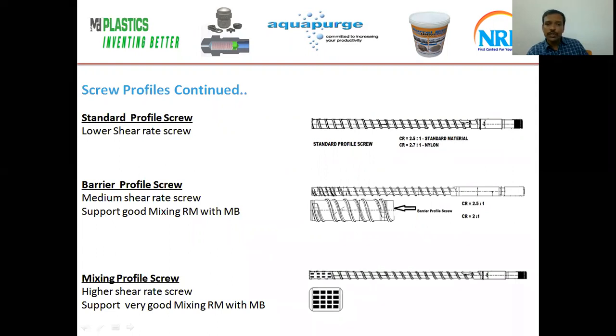Normally the standard profile screw has a lower shear rate, and the barrier profile screw has multiple plates on the screw and has a medium shear rate of plastic material. It will support good mixing when we mold raw material with the master batch. The mixing profile screw gives a higher shear rate of processing material, but it supports very good mixing of raw material with the master batch.